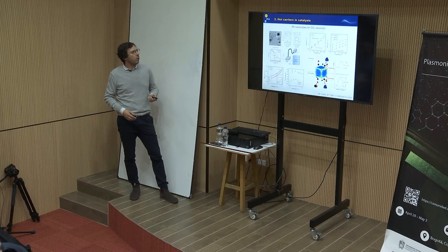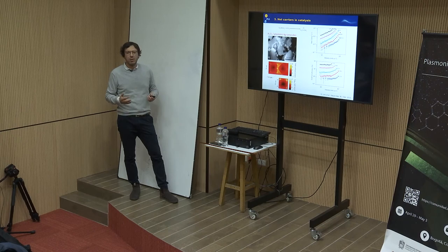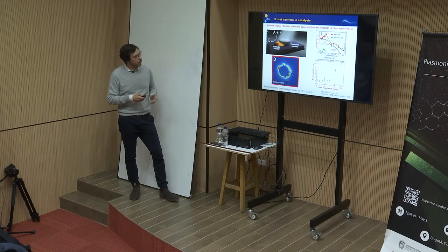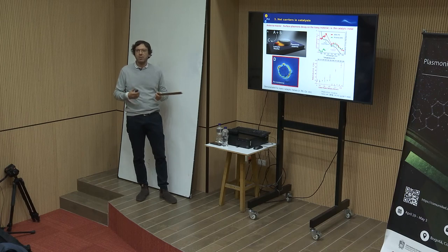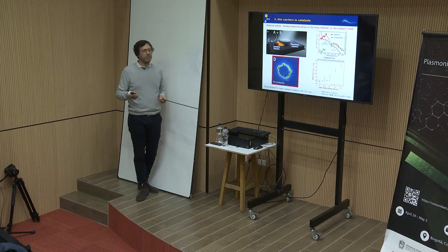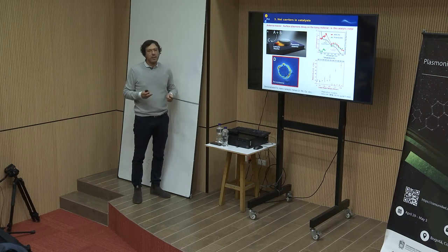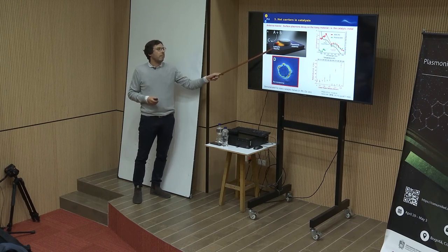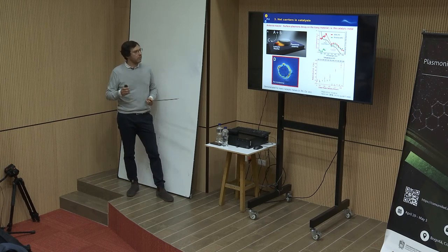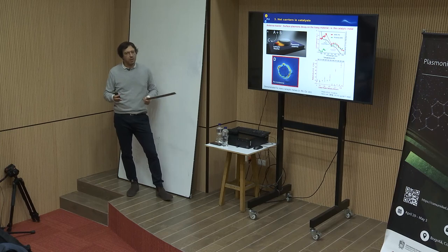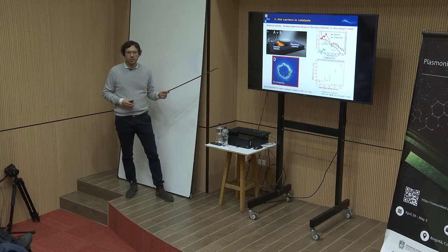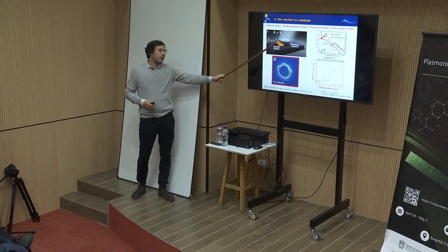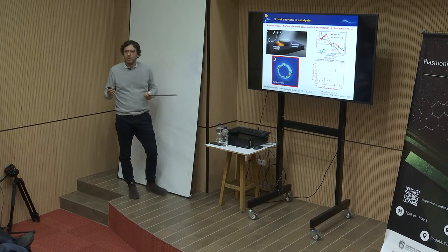So this is another example. All this material, all these examples, as I spoke about, were based on plasmonic nanocrystals. And what has been introduced later is this concept of the plasmonic antenna-reactor system. Basically, the plasmonic materials usually are not very good catalysts. Silver, gold, aluminium are very poor, lossy catalysts, but they are very good at absorbing light. Otherwise, metals like rhodium, palladium, platinum, all these traditional transition metals, are very good catalysts, but they are very lossy in the visible, and so they are not very good for creating resonating structures. So if you can couple these two properties into a hybrid structure, then you can absorb the light very efficiently, and you can use the particles of palladium or platinum to drive plasmonic catalysis.